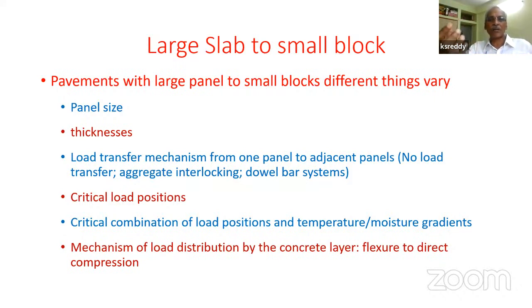That is a critical issue which will govern where the cracks would form, what will be the stresses that will be produced. And typically the thicknesses of large panels will be larger. As you reduce the panel size, you can actually construct concrete pavements with smaller thicknesses. And another very critical thing is what is the load transfer mechanism from one panel to the adjacent panel? Because when you place load on a pavement, it should distribute load over a much wider area, whether it is a block pavement or a large panel concrete pavement. We expect the adjacent panel to share load. But we have seen in some kinds of construction, where you construct the concrete layer panel by panel, there is no load transfer mechanism. Whereas when you create an interlocking mechanism, there is definitely load transfer. So creation of a load transfer mechanism across these panels is very critical for the performance of these pavements.